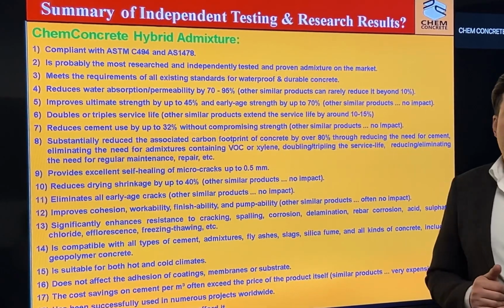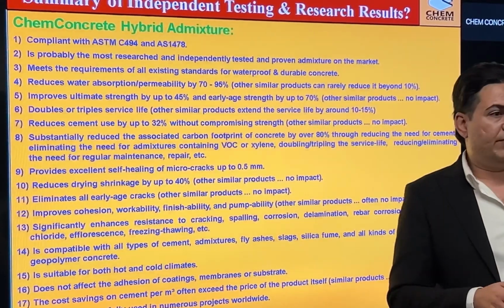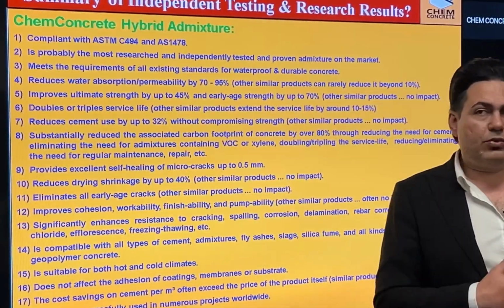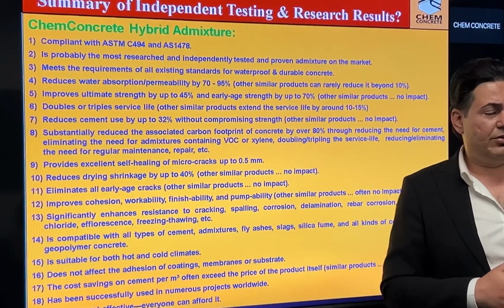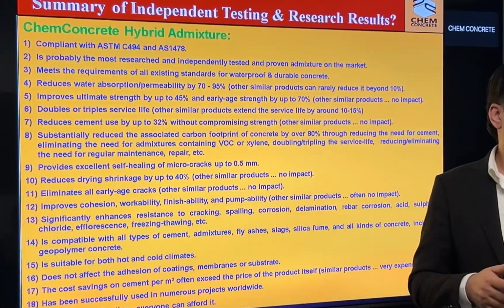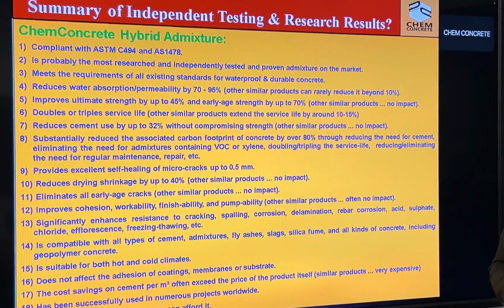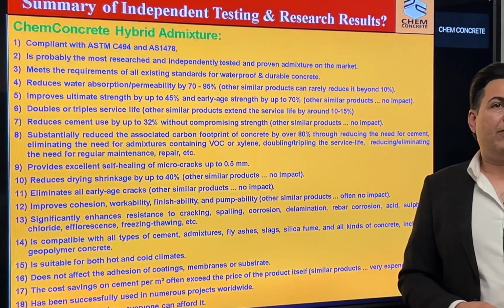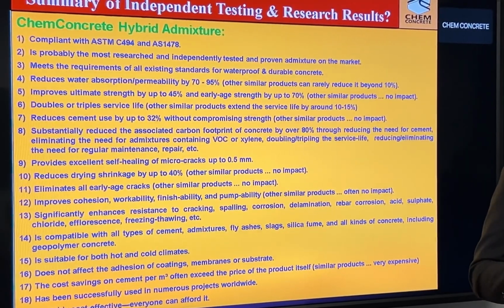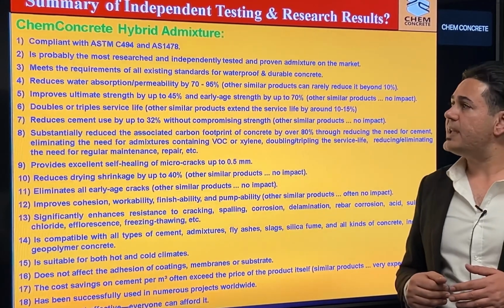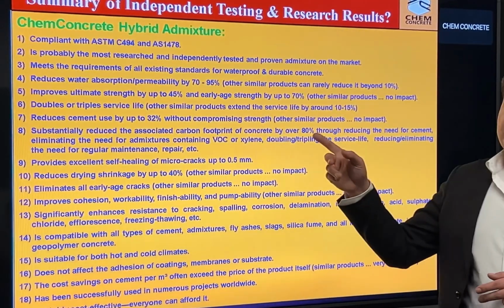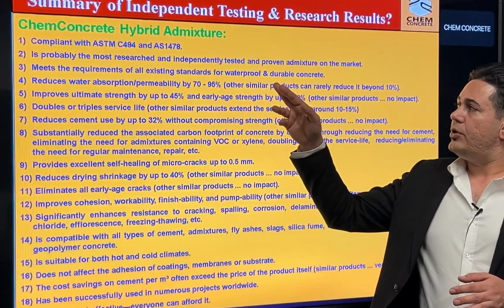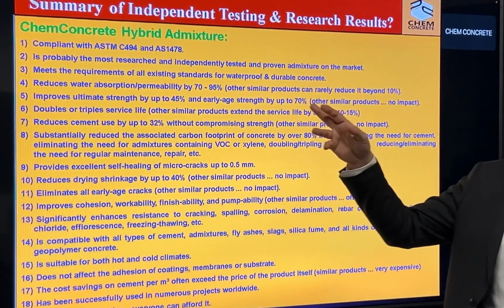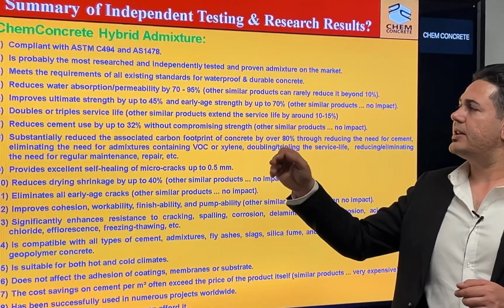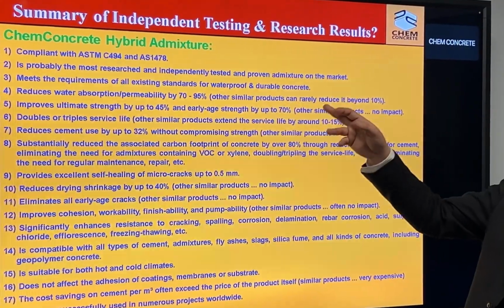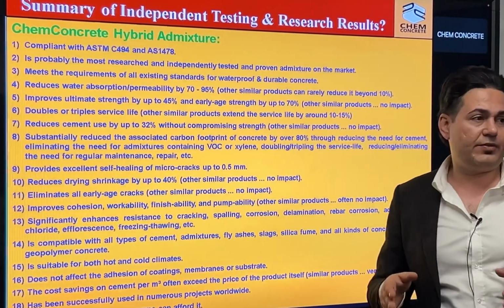So that's why we supplied around 4,000 concrete samples to different companies, laboratories, and universities all around the world. So far we have received around 190, 200 independent test reports from these companies in different countries. And the good thing is that all these independent test reports have reported almost the same results as what we have reported in our technical documents. For example, the product successfully passed all the requirements of ASTM C494, tested by SGS Tech Services in the USA, a well-known ASTM accredited lab, as well as Bora in Australia, and we received AS1478. So it has 2 compliance certificates from Australia and the USA.